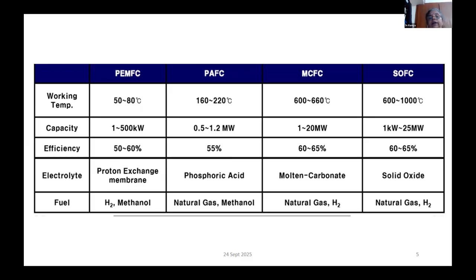If you are looking at a working temperature of 160 to 220 degrees centigrade, phosphoric acid is the go-to technology. The advantage of going from low temperature to higher temperature is that your hydrogen need not be very pure. In case of PEMFC, your hydrogen has to be more than 99.999% pure, five nines actually. Then only your fuel cell will have a long life. So if your hydrogen is from a reformer, where it can contain some amount of carbon monoxide, a few ppm, it is better to go for phosphoric acid based technology, because at the higher temperature the catalyst can withstand this kind of poisonous gases and performance can still be retained.